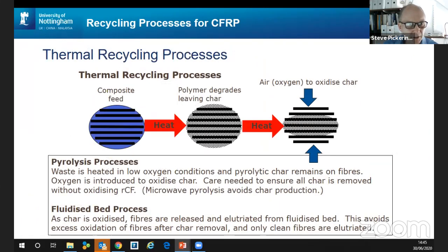Just wanted to say a few words about the way in which these thermal recycling processes work, particularly the fluidized bed and the pyrolysis processes. You'd start off with a composite feed and you'd heat it, and the polymer degrades and leaves behind a pyrolytic char as well as the fibers. So you can see here we've got the fibers embedded in some resin. Here are the fibers. After initial pyrolysis, there's still some char holding the fibers together.